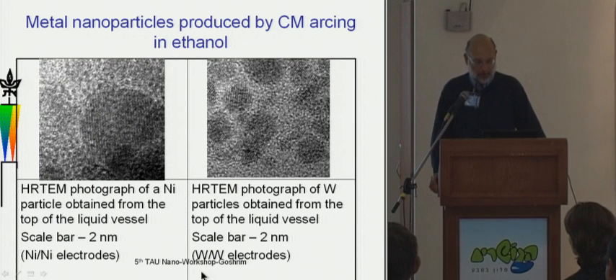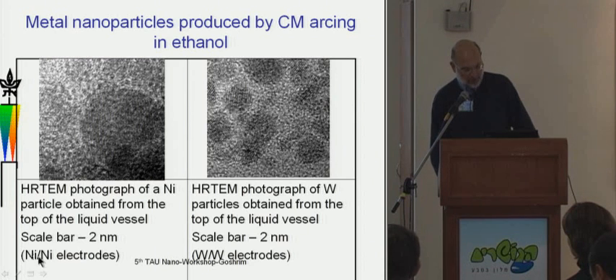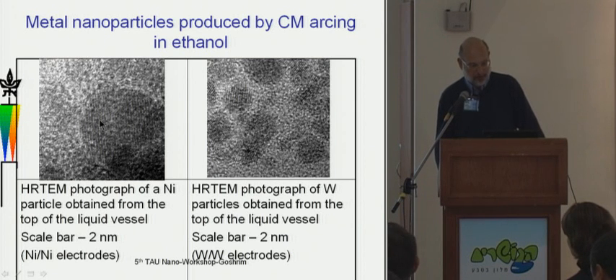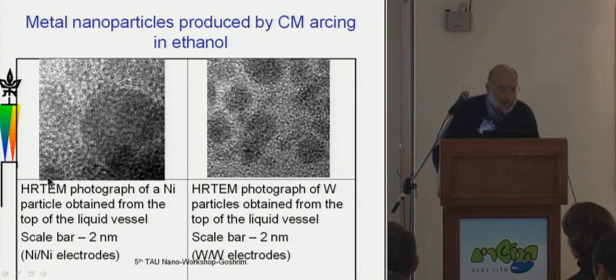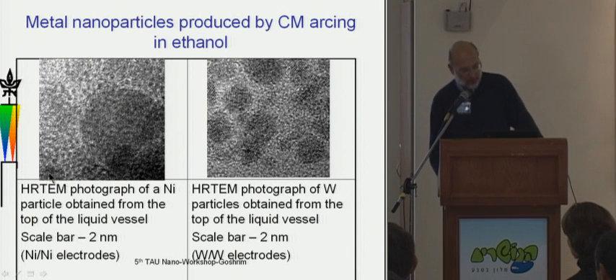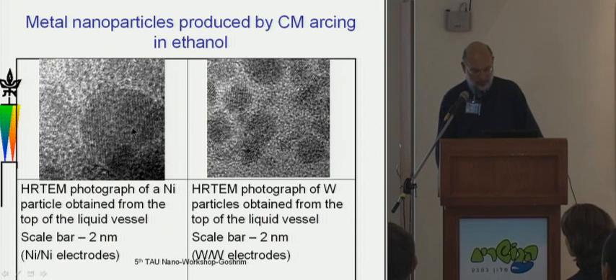For example, if we use contact mode arcing in ethanol from a pair of nickel electrodes, we find floating near the top of our beaker of liquid nanoparticles. I think the scale bar here is 2 nanometers of crystalline nickel, or if the electrodes were tungsten, nanoparticles of crystalline tungsten.